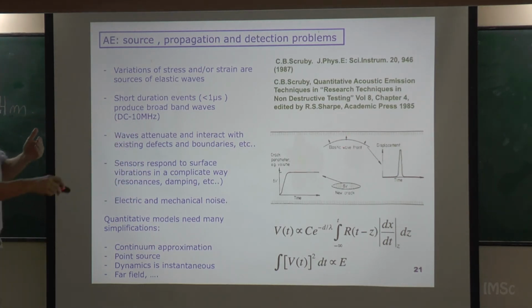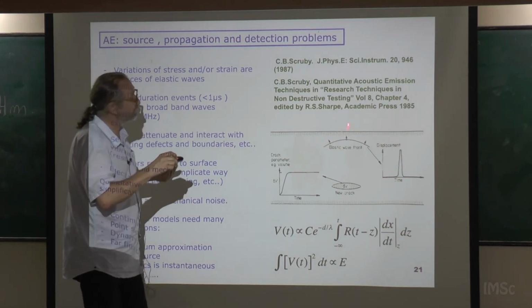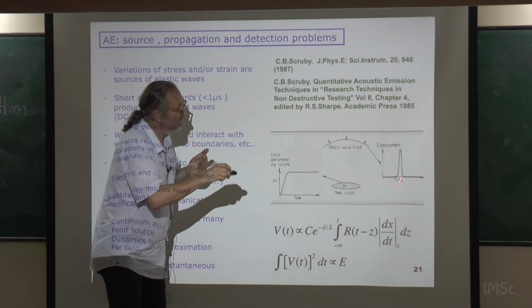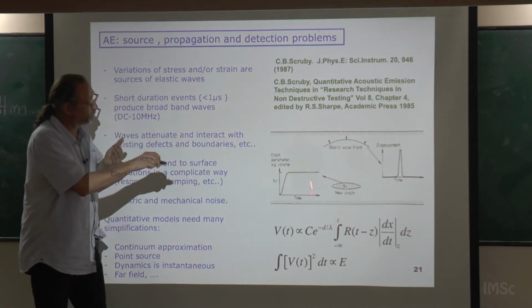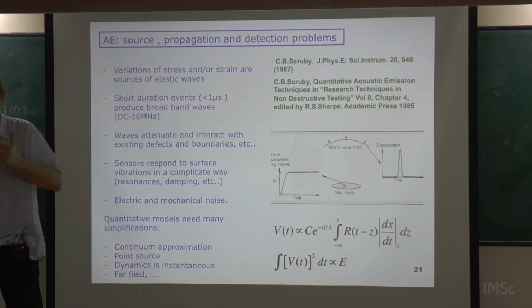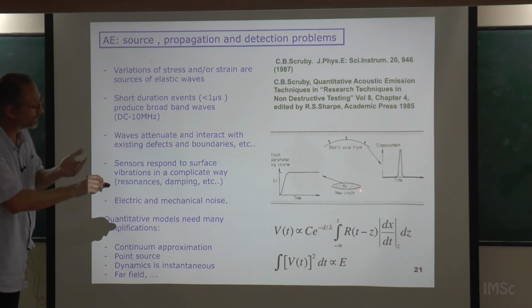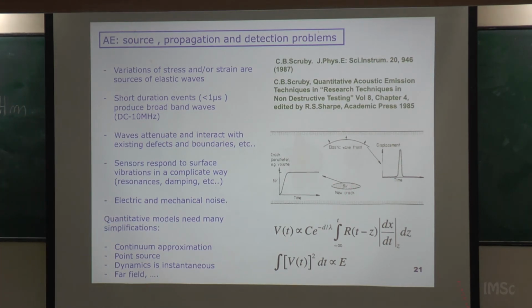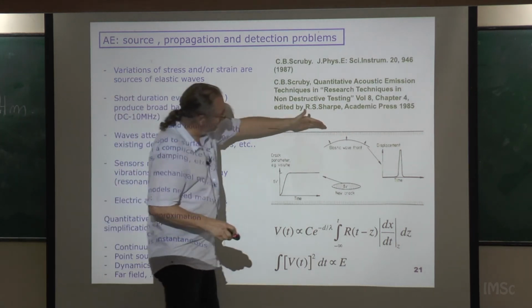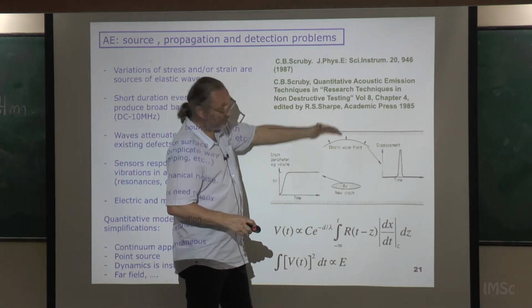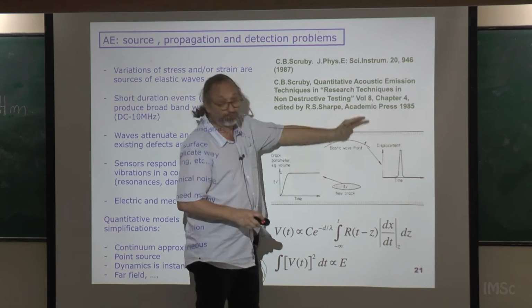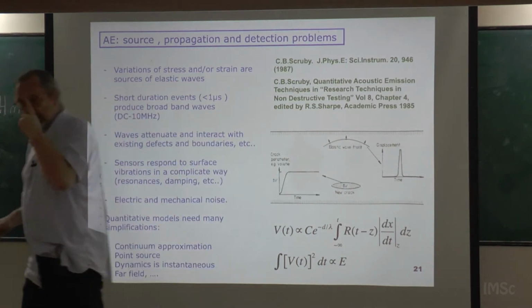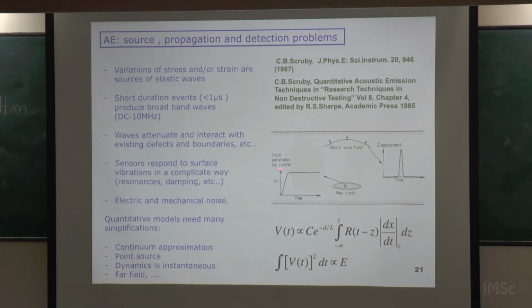And here in the surface, what you get is a wave, a displacement, that in fact corresponds to the derivative of this change. So in fact it corresponds to the speed of this change. So essentially what we do is put sensors here that detect the waves that arrive due to the fast movement of internal interfaces. Okay, this is what we do in acoustic emission.